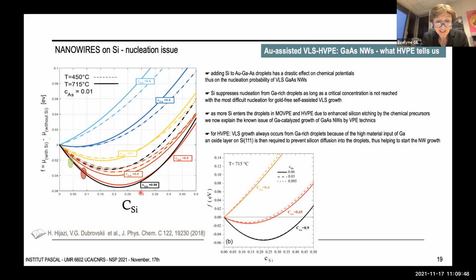So Vladimir Dubrovsky and Hadi Hijazi calculated the chemical potentials involved in the catalyst droplets. And they show that adding silicon to these droplets had a drastic effect on the nucleation of gallium arsenide nanowires. And these curves must be read like this. If F is negative, which occurs, as you can see here, for high gallium concentrations, then the chemical potential in the droplet with silicon is lower than without silicon. It means that adding silicon to gallium-rich gold-gallium droplets makes the initial nucleation of gallium arsenide nanowires more difficult.